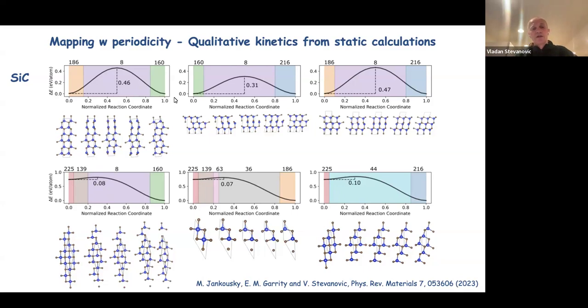And if you compare this to experimentally known facts, you will find that these tetrahedrally coordinated structures, meaning wurtzite, rhombohedral, and zinc blende, are all long-lived metastable phases. So they can be stabilized. And these barrier magnitudes, on the order of about half a volt, 500 millivolts per atom, are usually considered high for bulk barriers. Whereas for the barriers related to the transformation of rock salt, which is octahedrally coordinated, into these other tetrahedrally coordinated structures, they are much smaller in magnitude. So basically by a factor of 4, and they're all around 100 millivolts per atom or less.